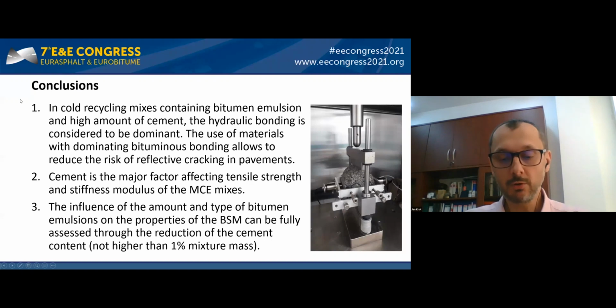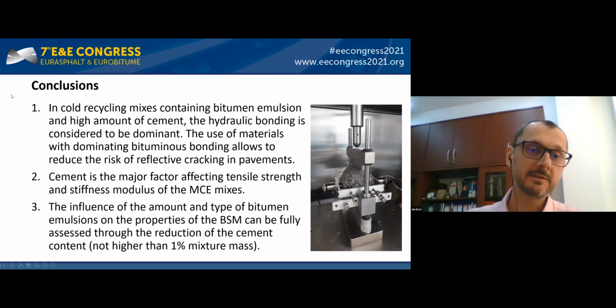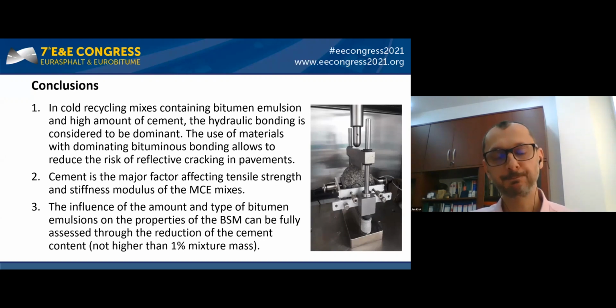And going to conclusion, it could be stated that in cold recycling mixes containing bitumen emulsion and a high amount of cement, the hydraulic bonding is considered to be dominant. The use of materials with dominating bituminous bonding allows to reduce the risk of reflective cracking in pavements. Cement is the major factor affecting tensile strength and stiffness modulus of the MCE mixes. The influence of the amount and type of bitumen emulsion on the properties of the BSM can be fully assessed through the reduction of the cement content to not higher than 1% of mixture by mass.